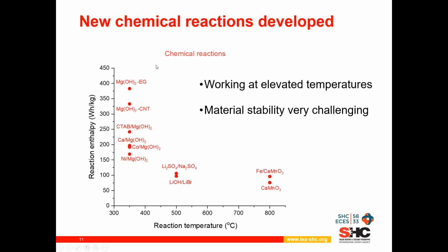Another example is for the chemical reactions. Note that here the temperatures are much higher, starting with 300 degrees centigrade up to 800 degrees centigrade. And here is the reaction enthalpy depicted. So typical reaction enthalpies are very distributed for the different materials. Here, the champion is the magnesium hydroxide reaction with expanded graphite, which shows that it's between 350 and 400 watt-hours per kilogram of enthalpy change at temperatures of about 370 degrees centigrade.